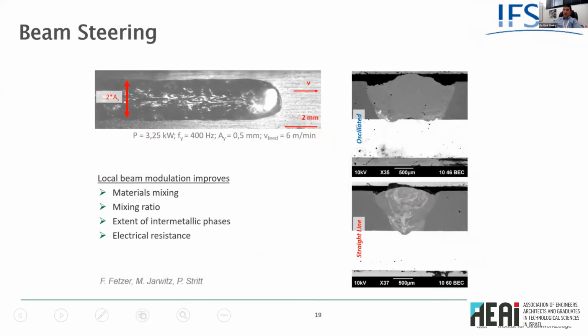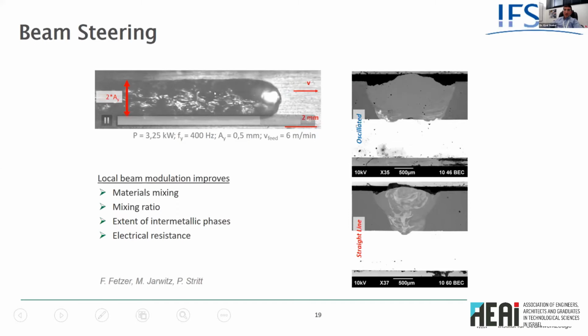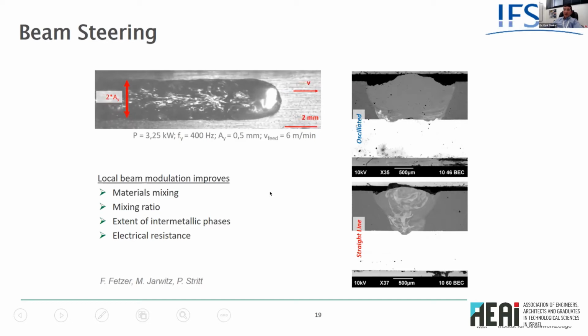Another similar example is overlap welding, when you want to weld copper to aluminum. If you just come with a single heat source or a standard stationary laser beam, you get mixing of the materials and you get a very poor quality weld. But if you move the beam around by oscillating the beam, you can control the width and the depth of the weld. You can control the lifetime of the melt pool and the temperature gradient of this melt pool, making sure that you don't have any mixing and no intermetallic phases, and just in general a very, very good weld.